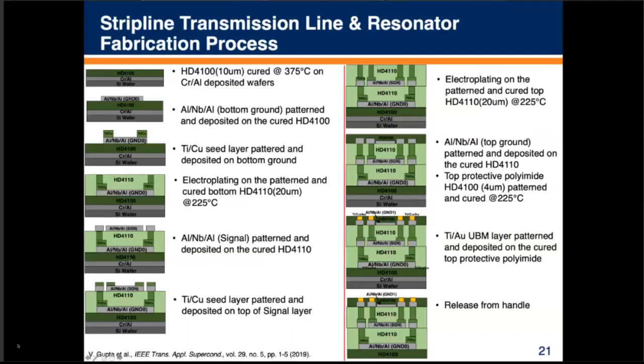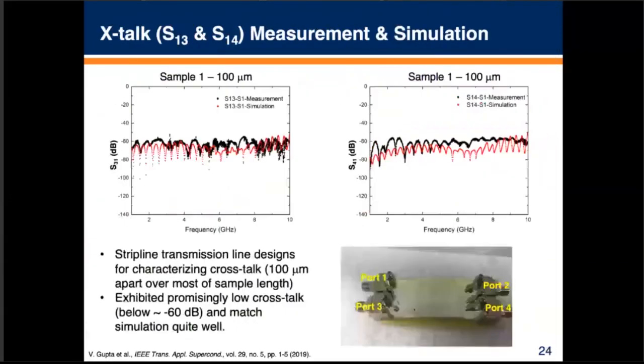So we just repeat that process multiple times, and at the end we end up with a ground layer, a signal layer, and then a top ground layer, and that gives us that strip line configuration with connections down to the signal layer and some underbump metallization on top to be able to connect to other structures, whether it's a connector or some of the face-to-face connection schemes that we've been working on more recently. So that's the strip line.